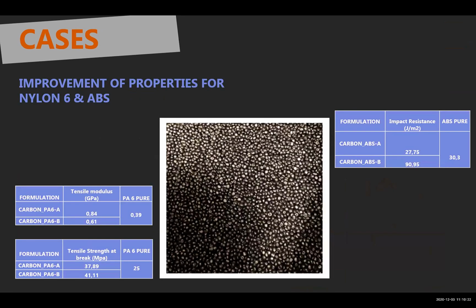And we have an entire market to apply this technology. So, in terms of mechanical properties, we know that it's not only about applying graphene in the polymer matrix. So we did a lot of experiments with different incorporation routes. As you can see here, when we are talking about the impact resistance with ABS, we tried two routes. In the route that I named A, we decreased the property, and in the route that we call B, we had a big increase. So one of the things of the Carbonup studies is, okay, we have the process of the customer, how much it costs to deliver this raw material, and how he can apply it, because if they don't apply it directly and correctly, they don't get the performance, so we don't meet the expectations of what we are selling.